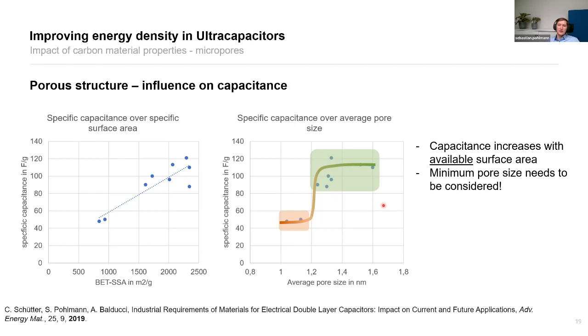So the impact of pore size in the end played a huge role, because you might have carbon materials that have very high surface areas but small pore sizes. And this is exactly what happens here. These data points are just on the brink of having a large enough pore size, and they have quite high surface areas, but the surface just cannot be utilized. So again, it is about checking what capacitance you get out, not only what the surface area is, but what the actual value is that matters in the application, which is capacitance.